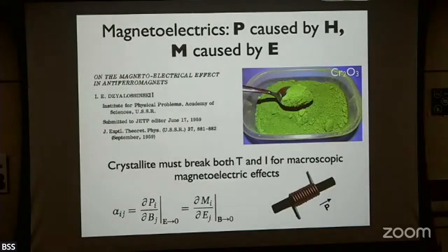So we've applied this to a lot of different things. One of these is topological insulators. And let me give you a brief interlude here about the notion of magnetoelectrics. Yesterday I wrote down this perturbative form of, say, the polarization as a function of electric field. I mentioned briefly that we can think about adding other terms. Sometimes these are cross terms of E and B, but I can imagine adding a term where I get polarization when I apply a magnetic field, or I get magnetization when I apply an electric field. That's not the usual state of affairs. We usually get magnetization when we apply a magnetic field, or polarization when we apply an electric field, but I can get these cross terms. That's called a magnetoelectric.